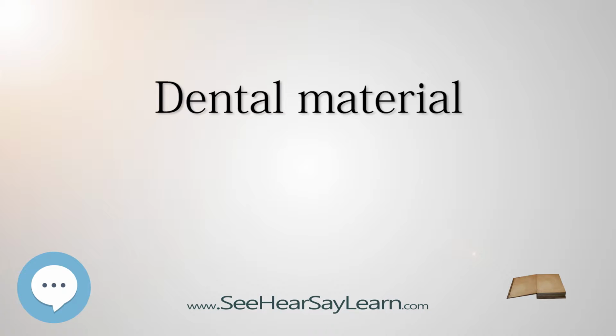The majority of clinical studies indicate the annual failure rates, AFRs, are between 1% and 3% with tooth-colored fillings on back teeth. Note that root canal, endodontically, treated teeth have AFRs between 2% and 12%. The main reasons for failure are cavities that occur around the filling and fracture of the real tooth. These are related to personal cavity risk and factors like grinding teeth, bruxism.